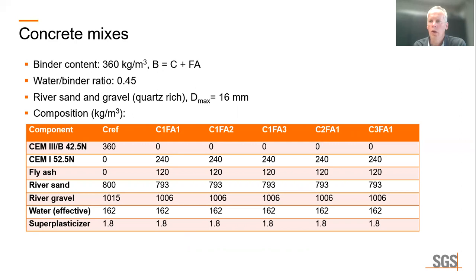If we now take a look at the concrete mixes, then in this table, the full concrete composition is shown. For all concrete mixes, the binder content was 360 kilograms per cube. And for the fly ash concrete mixes, the binder content is the total weight of cement and weight of fly ash. All concrete mixes had a water binder ratio of 0.45.